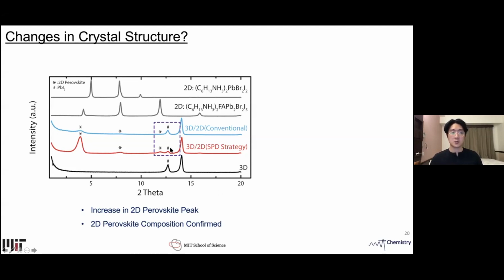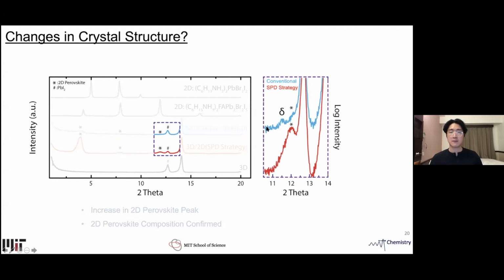Now if we zoom in to this specific range, where the conventional method is shown in blue trace and the SPD strategy is shown in red trace, we see that there is a detectable amount of delta phase for the conventional method, suggesting that the SPD strategy suppresses the formation of the delta phase.